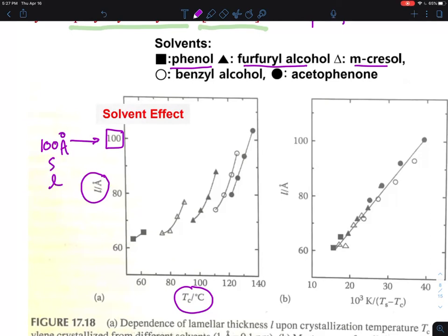They are changing the crystallization temperature. And then they measure the resulting lamellar thickness in a unit of angstrom. So this is one good reference point. About 100 angstrom is the lamellar thickness. But depending on the sizes or the crystallization conditions, you will have different sizes. And the higher the temperature that you have, the slower crystallization it will be.